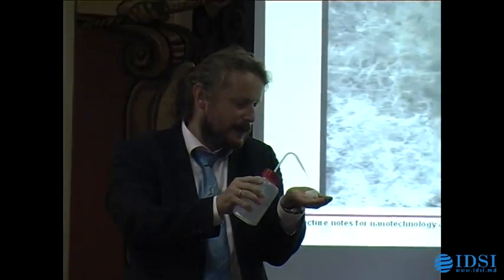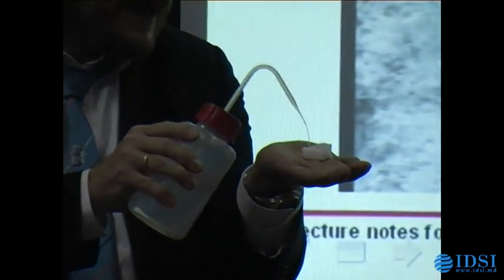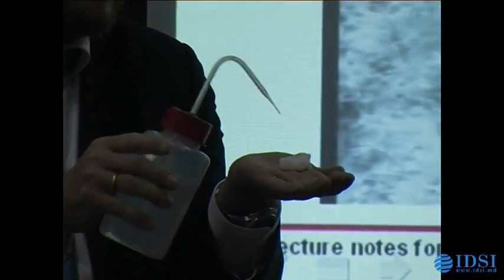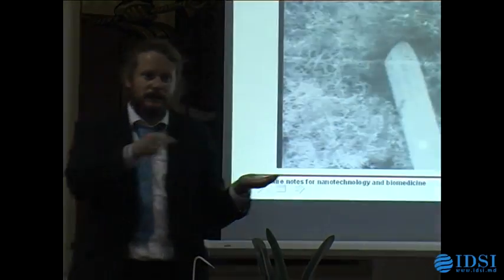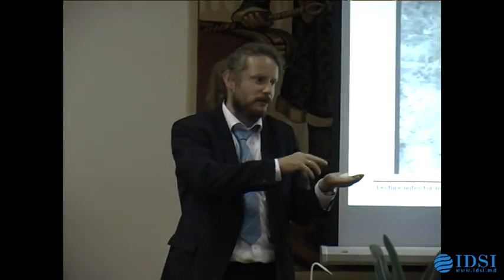And you see there's no droplet staying. It directly soaks in the water. I don't know if you can see this, but the water goes directly in. Actually, it looks like it's getting a little bit tinier. Why is that? Well, we talked about capillary force. The zinc oxide is a very polar material. If it's unprotected to water, the water really likes it. And it likes to compress the material inside, so it takes these capillaries together and is grabbing the arms and bending all these tetrapods. And now it's feeling a little bit like a kitchen sponge or something like that.